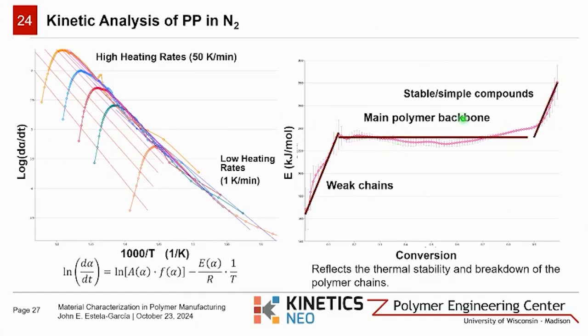And finally, we encounter this high activation energy region, and this corresponds to the scission of the most stable polymer chains, lower molecular weight species that remain after this. So as degradation progresses, the activation energy increases because the remaining material consists of simply more thermally stable structures. It's crucial to note that recycling processes can alter this profile simply by introducing new weak points or changing the distribution of chain lengths in your system.